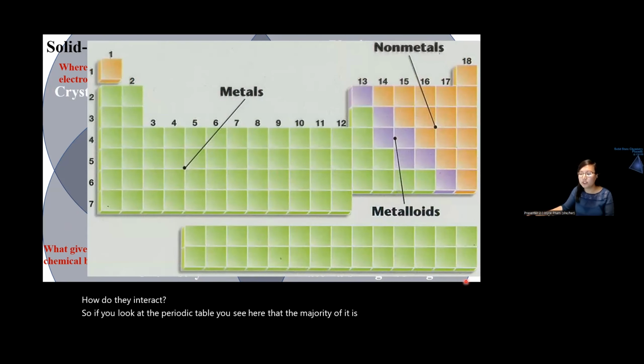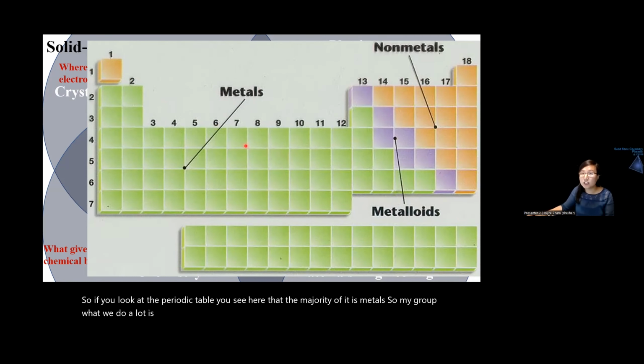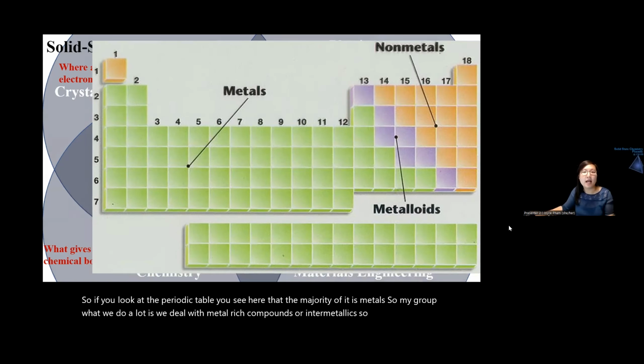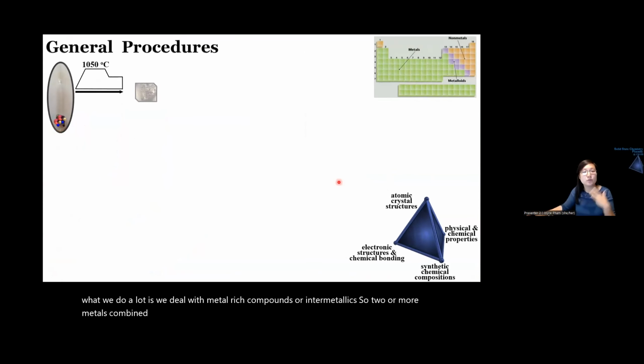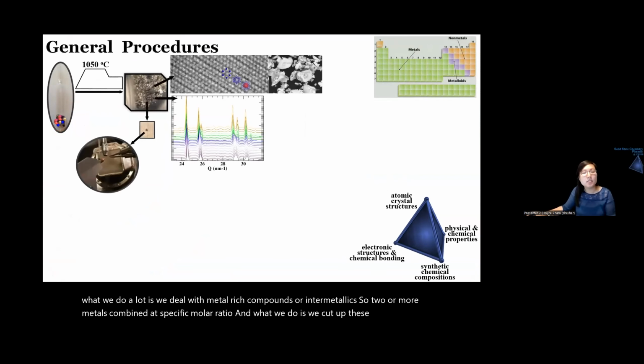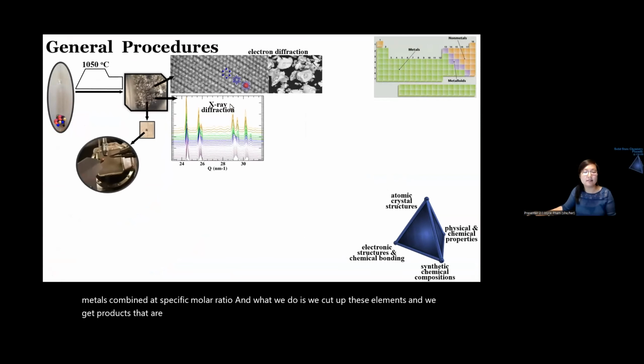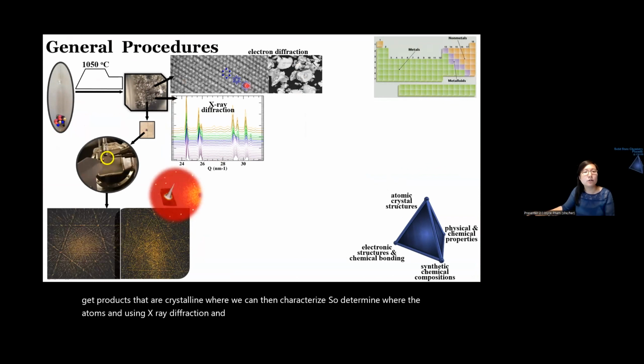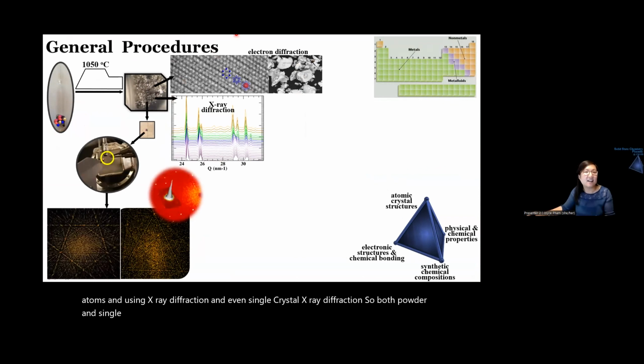So my group, what we do a lot is we deal with metal-rich compounds or intermetallics. So two or more metals combined at specific molar ratio. And what we do is we cut up these elements and we get products that are crystalline, where we can then characterize, so determine where the atoms are using X-ray diffraction and even single crystal X-ray diffraction. So both powder and single. And so these are data from our actual research group that you see here.